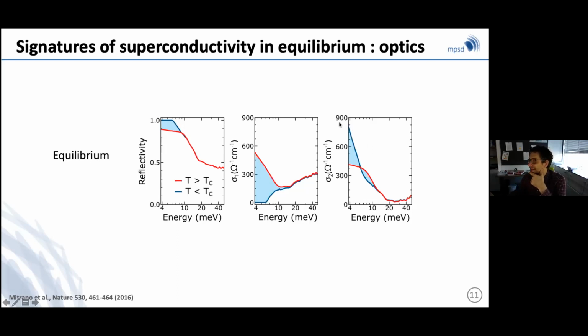So the fact that I see this divergent sigma 2 is indicative of a lot of spectral weight piled up at 0 frequency. These are the features of an S-wave superconductor at frequencies comparable to the superconducting gap. So, as I've said: a gap in sigma 1 and a divergent sigma 2.